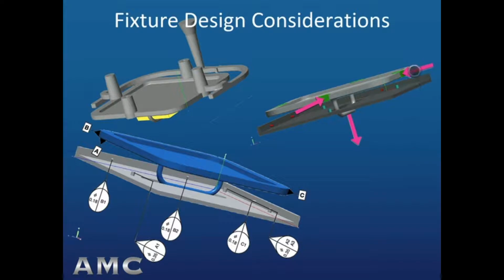It is okay to push against those for clamping, but they should never be used for datum targeting because they are hand cut and hand ground to match the casting's molded profile. Too uneven to be used for targeting. The handle feature is used to pull the casting down in the fixture against the three datum A targets. As we saw in the prior ductile iron casting example, the two datum B targets and single datum C target touch the drafted perimeter of the casting's rectangular profile.